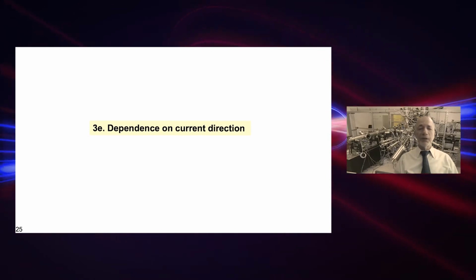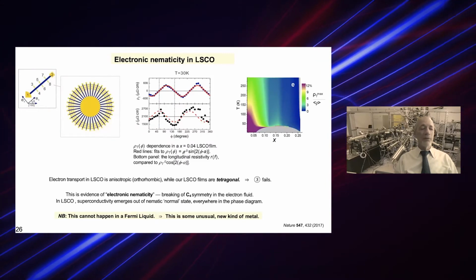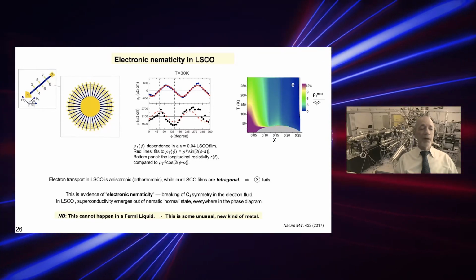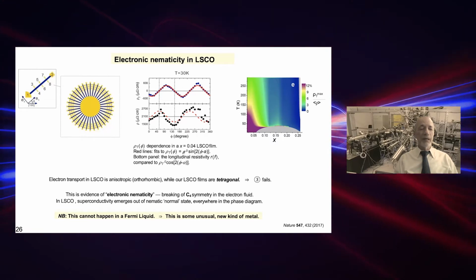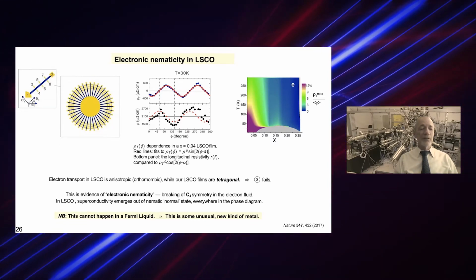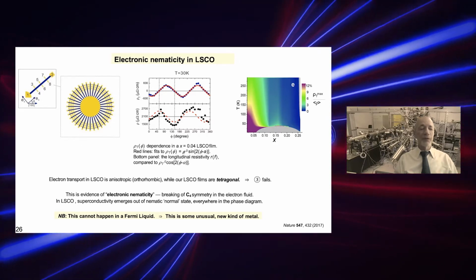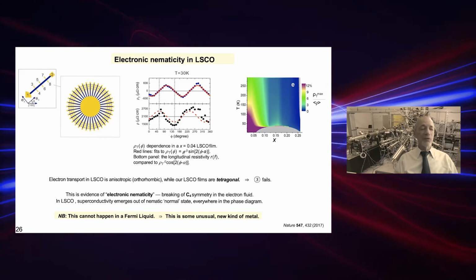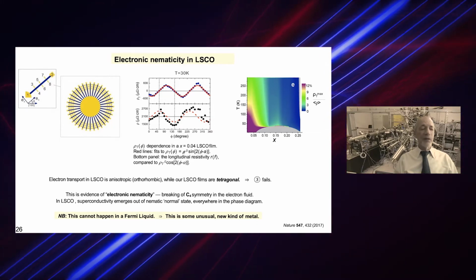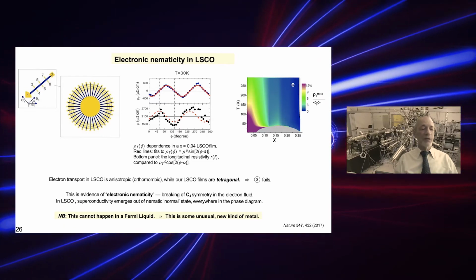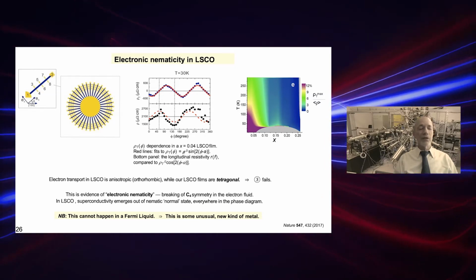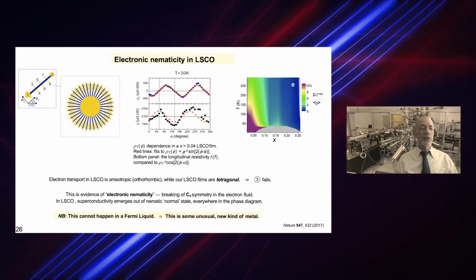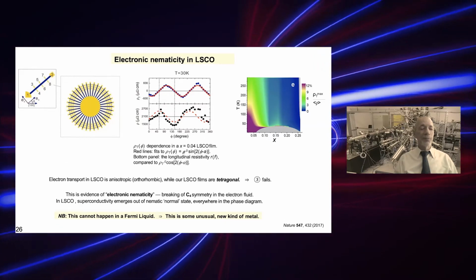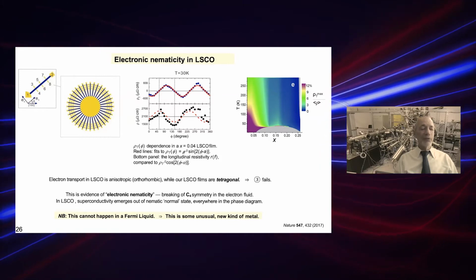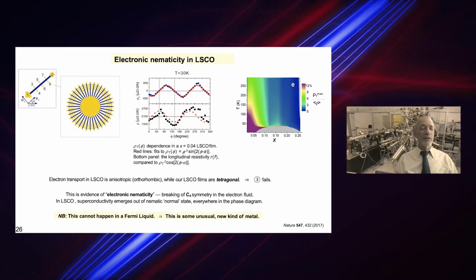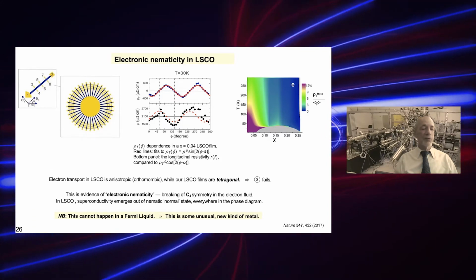Now, let's look at the dependence on the current direction. We have studied this systematically by using a new technique that we call angle resolved transverse resistivity measurement. So we patterned the films into a sunbeam pattern of 36 Hall bars at 10 degrees from one another, and then we measured both the longitudinal and transverse voltage at many angles. We found that as a function of in-plane orientation, both the transverse and longitudinal resistivity showed oscillations with 2 periods and 4 nodes. The amplitude remains the same, but the phases are shifted by 45 degrees between transverse and longitudinal.